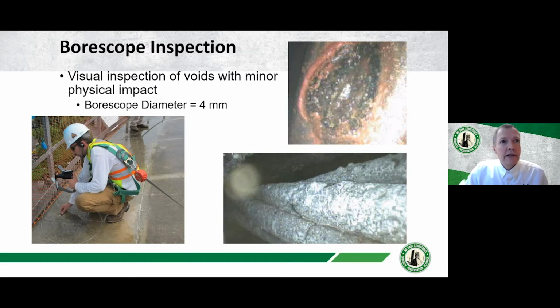And in this slide, you can see on the left-hand photo, one of my colleagues, Brian Pales, on top of an LNG tank that is post-tensioned. It has both horizontal post-tensioning and vertical post-tensioning in the shell. He has a borescope in his hand, and the probe from the borescope is being inserted into a small drilled hole that is going in where the old grout vent tubes were. From that drilled hole, you can take a look inside, and you can see where a void was identified, and you can see the condition of the strand.